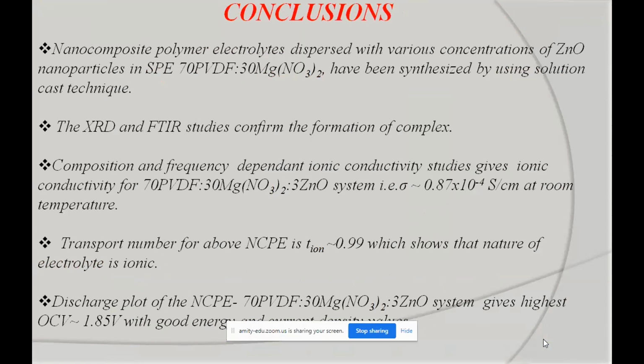Now, conclusion. In our work, we synthesized a series of nanocomposite polymer electrolytes dispersed with ZnO nanoparticles to enhance their electrical conductivity, mechanical stability, and other properties. These films are prepared by the solution casting method, and XRD and FTIR results confirm the formation of complex composition. Frequency dependent ionic conductivity studies give our ionic conductivity. We got the highest value, 0.87 × 10 to the power minus 4 Siemens per centimeter at room temperature, for our optimum system, that is 70% of PVDF, 30% of magnesium nitrate, and 3% of ZnO system.